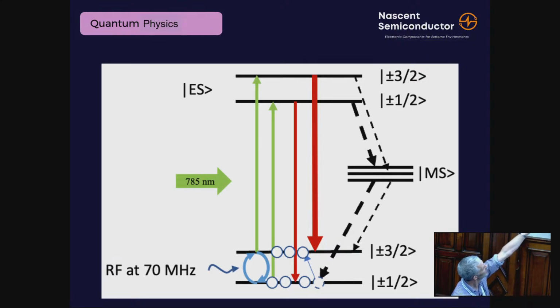And there's two options. If you're in a spin 3/2, it drops back to the spin 3/2 ground state, the big red arrow, and that's the dominant transition. That gives out light. This is a photoluminescence type measurement. If you're in the spin half, chances are it drops to this metastable state and drops back out at the bottom. This is a dark transition. We can't see it. We've got no idea that it's there. We know it's there. Physics tells us it's there, but we can't actually see this. It's called the dark defect.